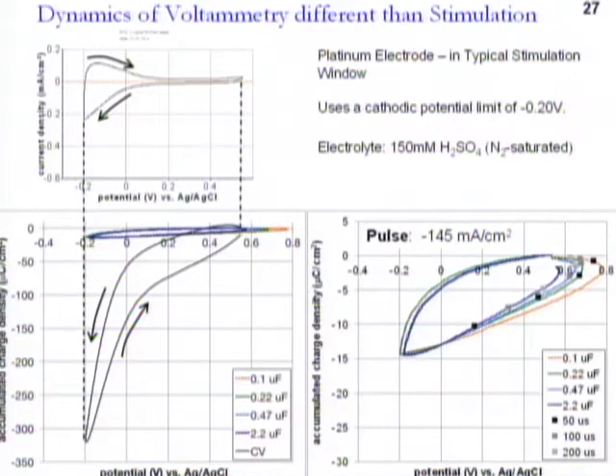just comparing that time scale. Again, we're using voltammetry for preliminary evaluation, and that's on the order of seconds that you take the measurement. When you do the pulsing, you're doing something on the order of microseconds. And if you just compare the charge that gets transferred, this large amount of charge here is from the Voltammogram. And if you do the equivalent change in potential by applying a pulse, the amount of charge is much less. So by changing the time scale, which is obviously the more relevant time scale, the amount of charge transfer you're seeing does seem to go down by quite a bit. And so maybe using voltammetry is not necessarily the best indicator of how much charge you're going to see at your electrode.